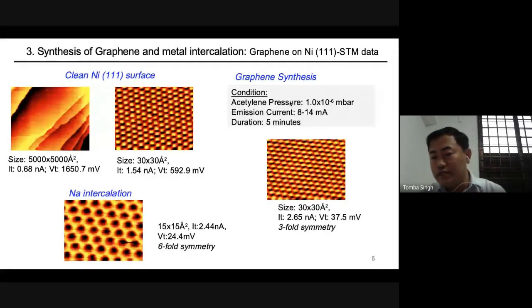On this we studied STM and found the formation of graphene. Here we see signals from only three atoms out of the six carbon atoms in the graphene hexagon. Why are three missing? This is because of a strong interaction between the graphene and the nickel substrate. They have very close lattice constants. In graphene it is 2.46 angstrom, and for nickel it is 2.45. So the lattice mismatch is 1.12%, very close. That's why they have a strong interaction.